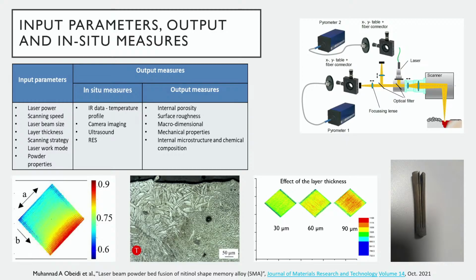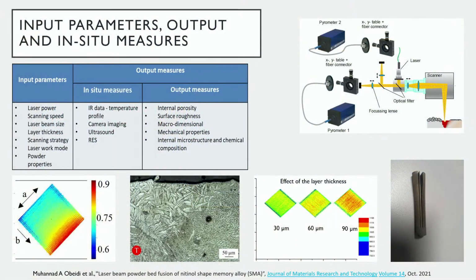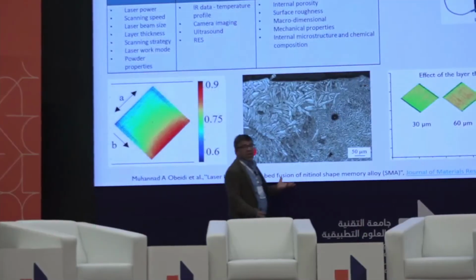weakness, let's say. The microstructure, see how big is the grain here compared to here. Larger grain here because of the lower cooling rate, smaller grain size here, and that's in one layer. The post-process here to overcome this problem is by heat treatment and annealing. Sometimes we find porosity like this or larger, this here.